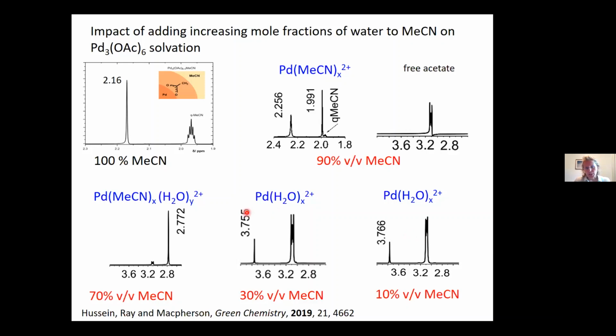What we did with proton NMR, we did UV-Vis, Raman, infrared, all told us the same story, that when you're in 100% acetonitrile, the acetate ligands want to stay very firmly attached to that palladium. There is no driver for the acetate to come off. Okay, so that means when you're doing electrochemistry in the acetonitrile, all you're doing is just changing from the 2+ to the 0 state, but it still remains solvated with its acetate ligands, and it will just move away from the electrode surface as in a standard sort of non-metal electrodeposition process.